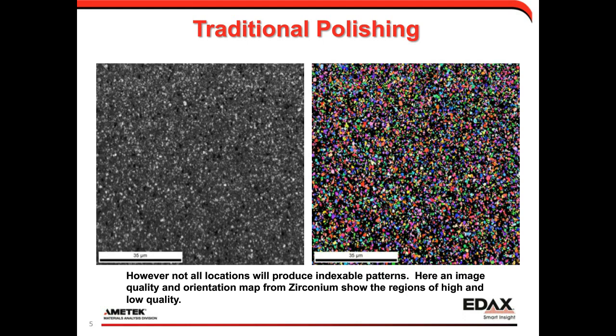But if we look at mapping this area, you'll notice here on the map on the left is the image quality map, where we see some grains that occur as brighter spots and that give us good diffraction patterns, and areas that are darker that do not give us as good diffraction patterns. And if we look at the map on the right, which shows us an orientation map where the good data is colored and the bad data is not colored, you'll see that the percentage of points that we can index with high quality is lower than what we'd really like. And the reason is polishing quality.